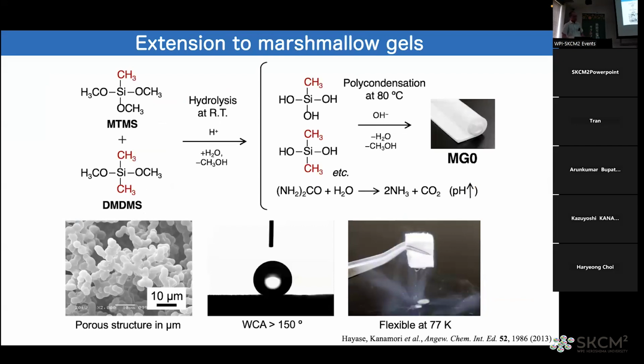So this is also an extension to very soft, flexible material, not starting only from MTMS, but also we use here the difunctional alkoxysilane, which makes the network much softer. But the network from these precursors is very hydrophobic, so it is difficult to suppress the phase separation completely. So the appearance of this gel is not transparent. This is white. So we named this gel marshmallow gel. It is not edible, but it looks like marshmallow.